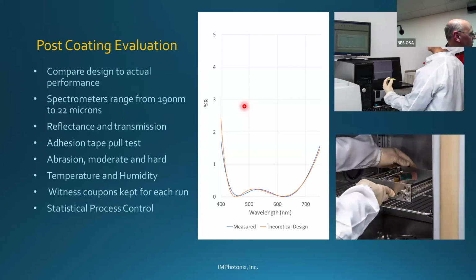Post-coating evaluation. We want to make sure that the coating we design and that we deposited meets the customer's expectation. So we use spectrometers ranging from 190 nanometers to 22 microns. There are dispersive spectrometers for the 190 to 3 microns, and FTIR for 2.5 to 22 microns.